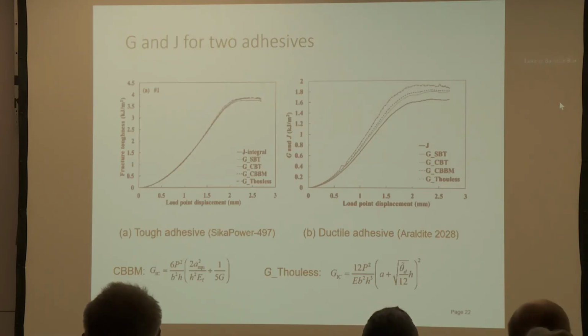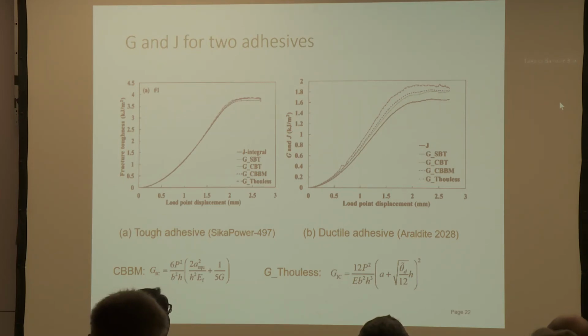So in terms of what it means for the adhesive, then we can compare, of course, G values via different techniques: simple beam theory, corrected beam theory, and different effective crack length approaches. And we can do that for different adhesives. So on the left, we're looking at a tough adhesive. This is a SikaPower-497. So this is an automotive adhesive, highly toughened and crash resistant. And we can see in this case that the methods are giving us pretty good agreement. The plateau value of J and G via the different techniques are quite closely correlated.